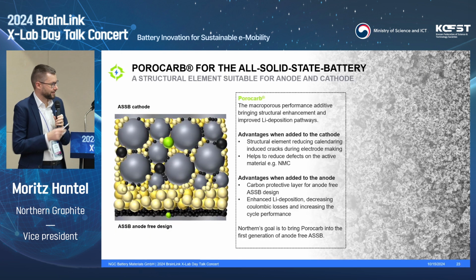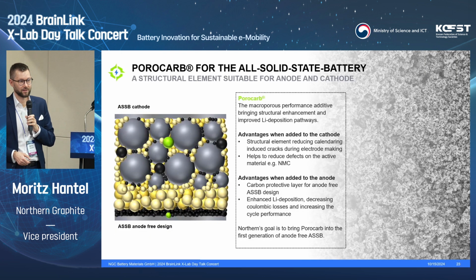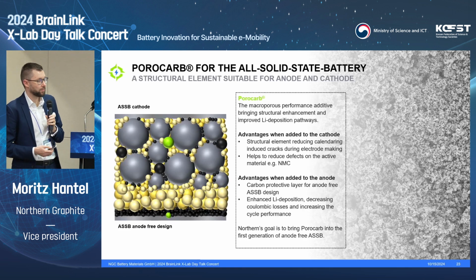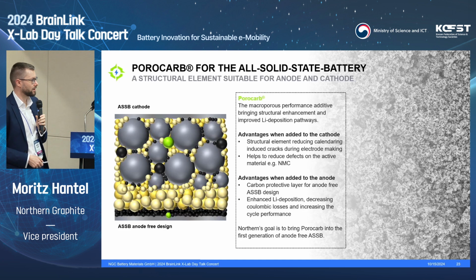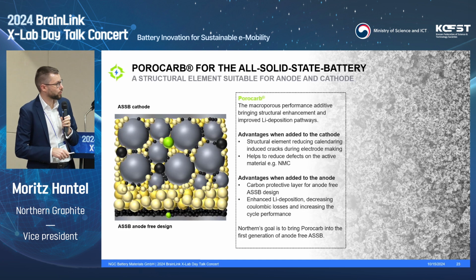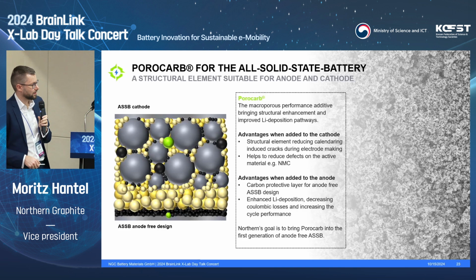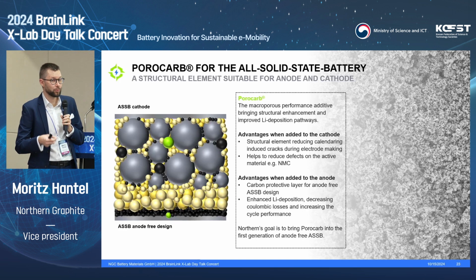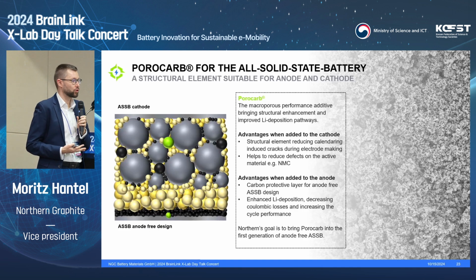The last part, and very similar to what we saw in the first presentation today, looking at the all-solid-state battery, you can also apply porocarb on both the cathode and the anode side. So in this case, you have in green the porocarb on the cathode side, and here in green on the anode side. And here the difference is that it's not about a liquid electrolyte. Here the porosity on the cathode side is not the main factor. It's more that you add a structural element, and what we see in customer projects is that by adding porocarb to the cathode, they are able to better densify their systems.